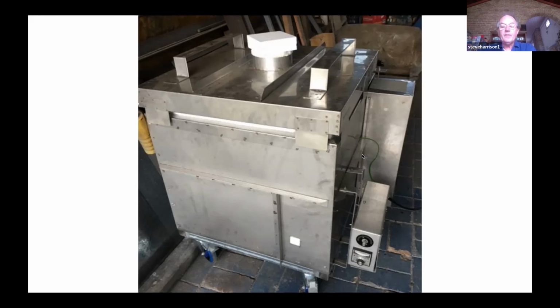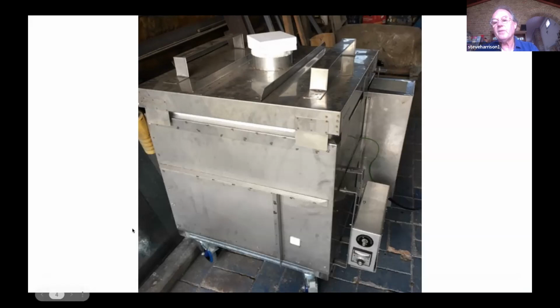Now, my friend Len Smith built a kiln sort of like this, and he went one better, and he used little tiny slivers of wood to create the reduction between 1,000 and 1,300. So that was a pretty good idea. I tried it, but I only did one firing because spending 3 hours sitting there putting tiny little slivers of wood into the hole every 5 minutes was pretty boring. It's kind of exciting when you first start to do it, but after a couple of hours, the fun kind of wears off. So I was happy to just let it run on propane, and it worked reasonably well. So can we have the next slide?